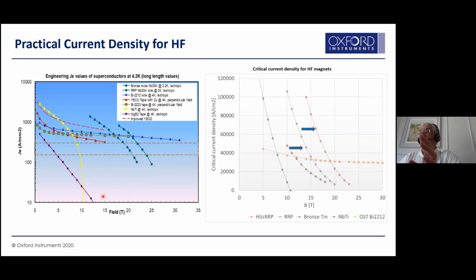If you want to go beyond 10 Tesla, the favorite will be niobium tin. But if you want to go beyond 20 Tesla, 22, then you have to think about high temperature materials like BSCCO 2212, BSCCO 2223, and YBCO. The other development that has been done over the years is to improve the performance of these low temperature superconductors. About 20 years ago, most of the systems were using bronze-based niobium tin material. Oxford Instruments' sister company, Oxford Superconducting Technology, which is now part of Bruker, has developed the RRP wire.